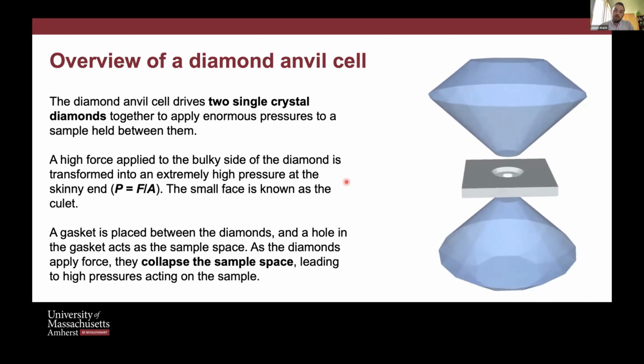So there's a question about what's the limit for how low in pressure you can go. If you know that you want to work below 5 GPa, for example, you would probably purchase large culets on the order of 500 to 1000 microns. If you know you want to go to 10 to 30 GPa, 300 microns; to a megabar, 100 microns. Stas had some good slides with details on that. But if not, just reach out and ask.